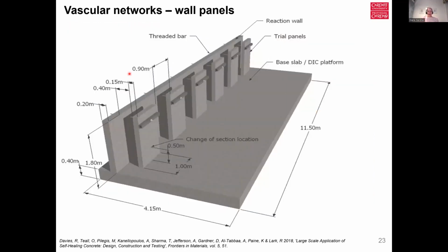This gave us confidence to go one step further and to look at including our vascular networks in a series of wall panels. Now, these were created in conjunction with our colleagues at universities of Cambridge and Bath, who tested their other technologies in some of the other wall panels. Altogether, 5 wall panels were made. Several walls had vascular networks placed within them, but only one was actually loaded with healing agent. The walls themselves were 1 meter wide, 1.8 meters tall, and 150 millimeters thick.